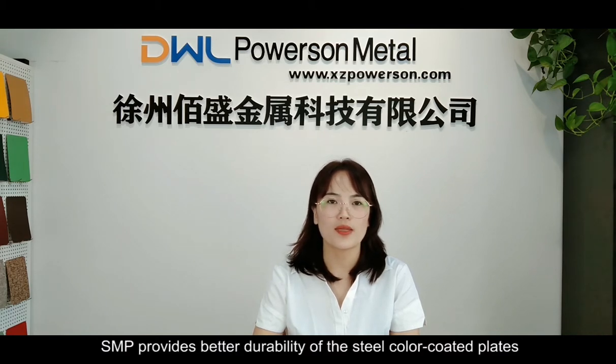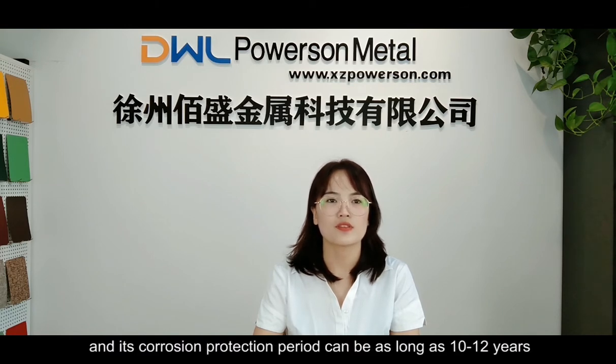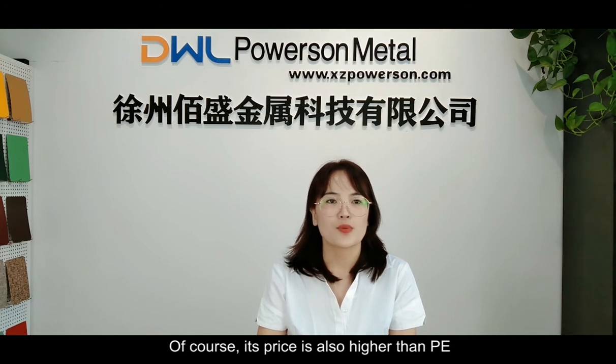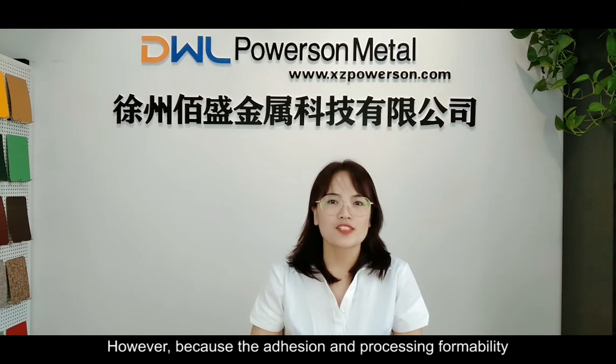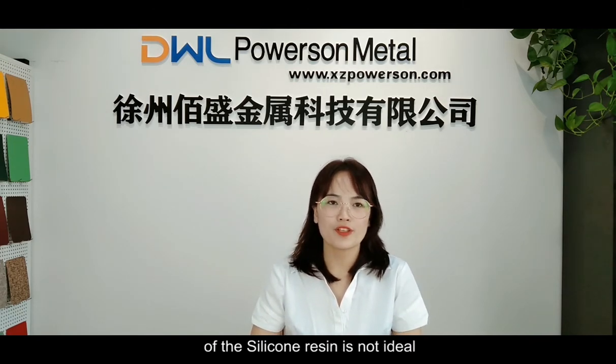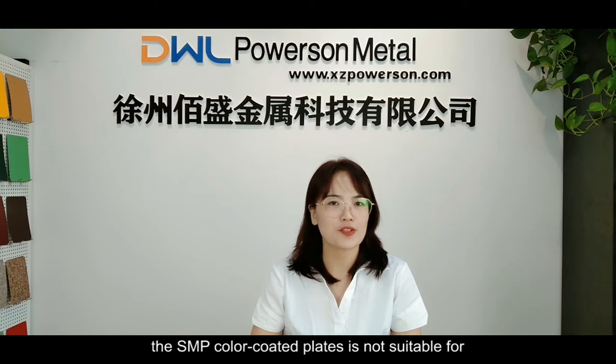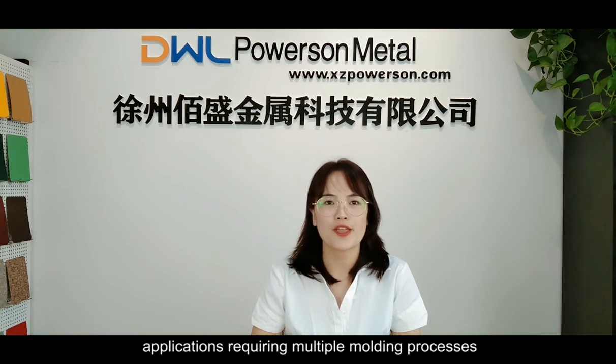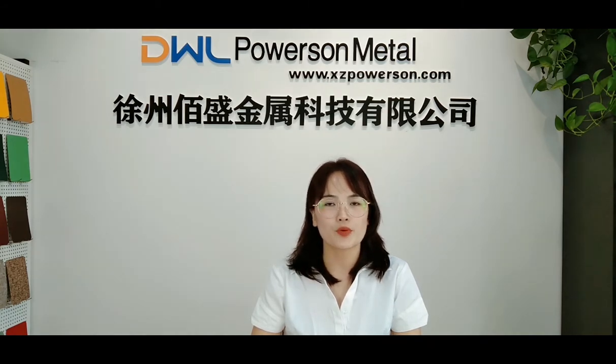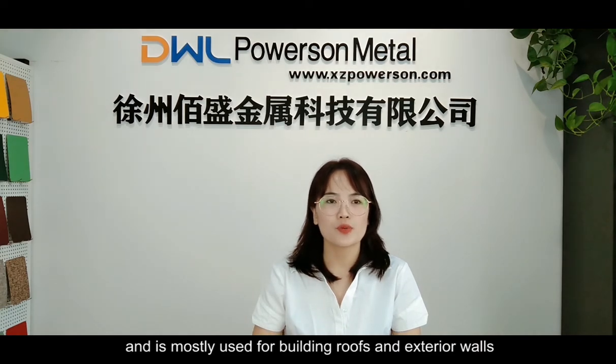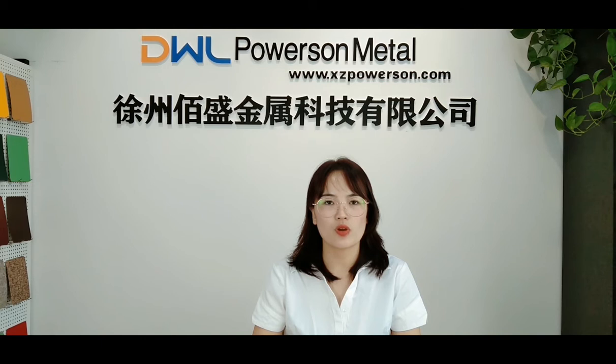SMP provides better durability of the color-coated steel plates, and its corrosion protection period can be as long as 10 to 12 years. Of course, the price is also higher than PE. However, because the adhesion and the process formability of the silicone resin is not ideal, SMP color-coated plates are not suitable for applications requiring multiple molding processes, and are mostly used for building roofs and exterior walls.